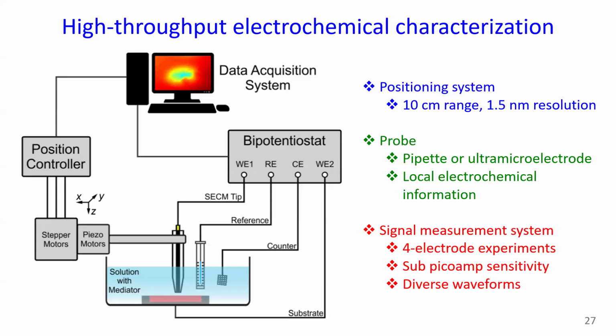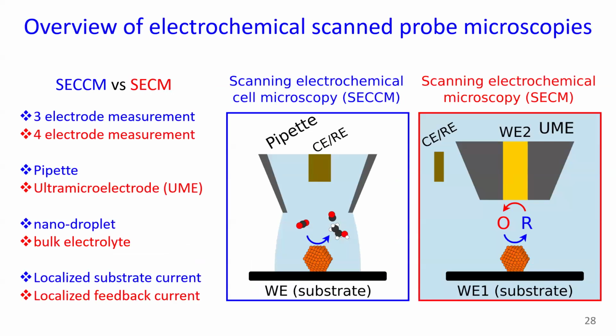The point being is our approach to high throughput experimentation is to make localized electrochemical measurements, and the way we do that is with scan probe microscopy. Similar to AFM or STM, it consists of a controller to move a probe and then an instrument to measure signals in that probe. In our case, we're measuring currents and potentials. And we can do this several different ways using related techniques. So we can have a pipette, which creates a meniscus at the substrate electrode, and essentially this is localizing the electrochemical cell.